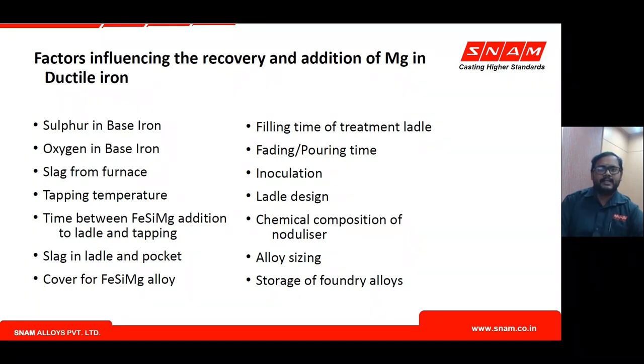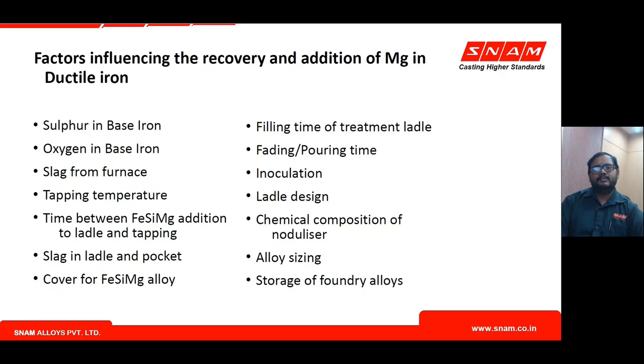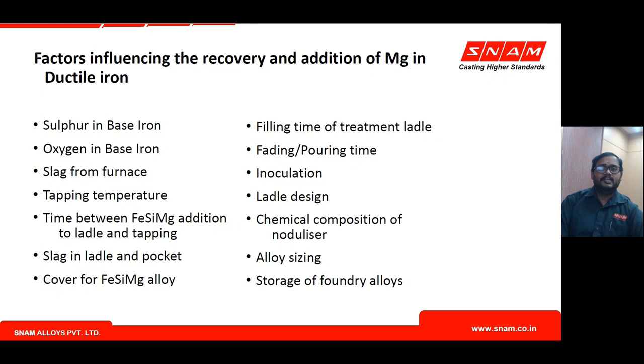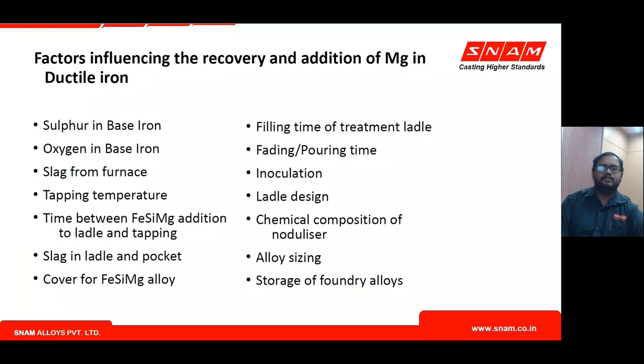Delaying the reaction ensures more metal is available on top before the reaction begins, so magnesium vapor doesn't escape and maximum magnesium is retained in the liquid metal. Filling time of the ladle and pouring time both directly affect recovery. People tend to use high-magnesium alloys to compensate for process variations, but this is not the correct approach — there are normal conditions where high addition rates or high magnesium content are unnecessary.